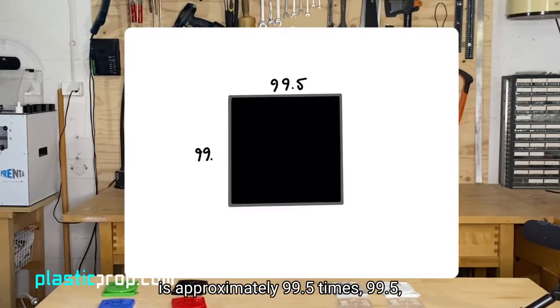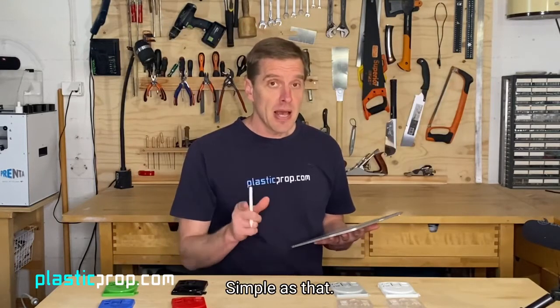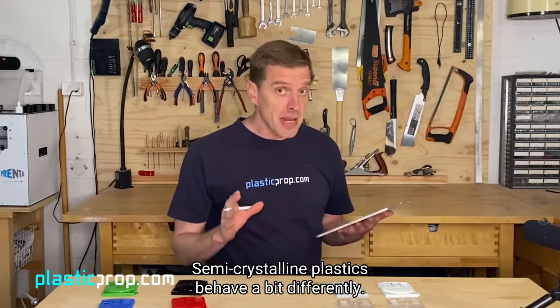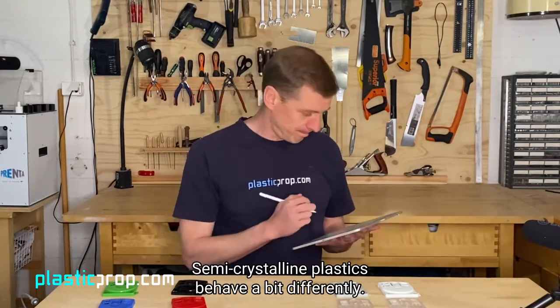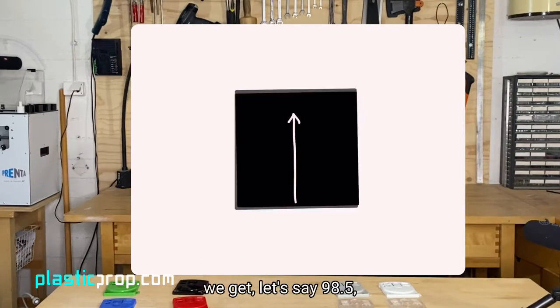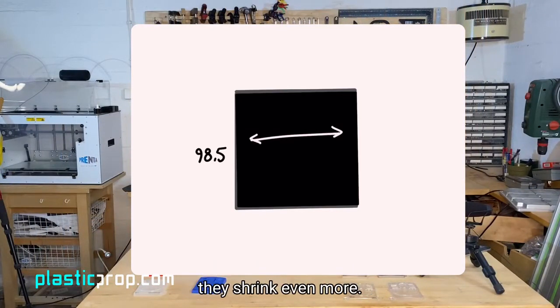So what we end up with is approximately 99.5 times 99.5. Simple as that. Semi-crystalline plastics behave a bit differently. They shrink more, so in the direction of flow we get, let's say, 98.5, but in the direction perpendicular to the flow they shrink even more, and for this reason we get, let's say, 97.5.